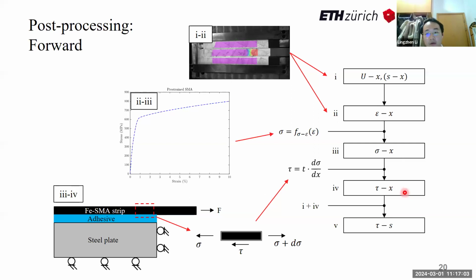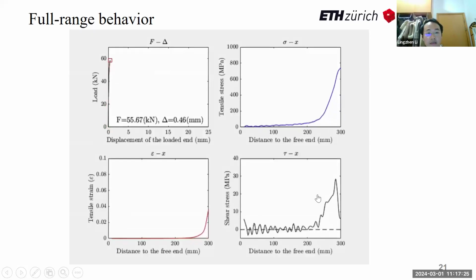The last step was to correlate the shear stress location behavior with the shear slip location behavior measured in the first step. We have the shear slip behavior of the bond line. This is an animation of the analyzed experimental behavior.